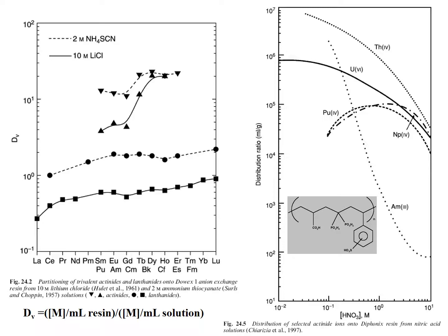Diphonix resin from nitric acid solutions. This is again a distribution coefficient, milliliters per gram. Again, rather large numbers, 10 to the 5th, 10 to the 6th. And we see as the nitric acid concentration increases, the distribution of the metal ions tends to decrease, the thorium, uranium, americium rapidly decreasing. The tetravalents increase, reach a maximum, and then begin decreasing. And then the lowest distribution is for the trivalents at the higher nitric acid concentration.